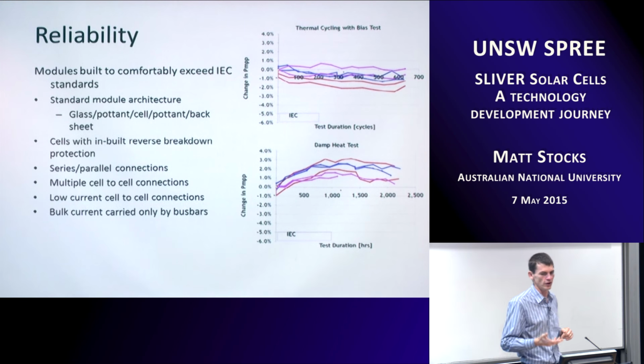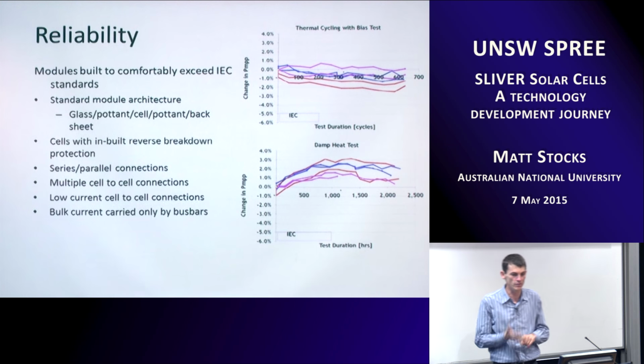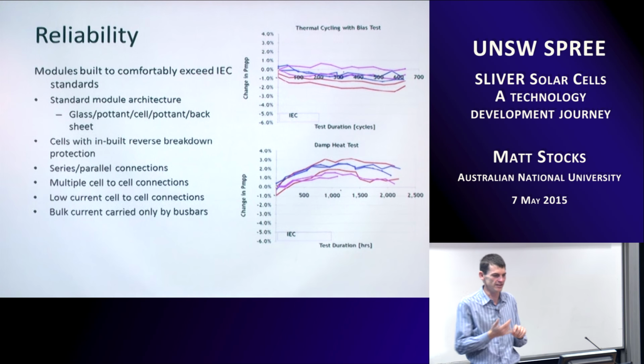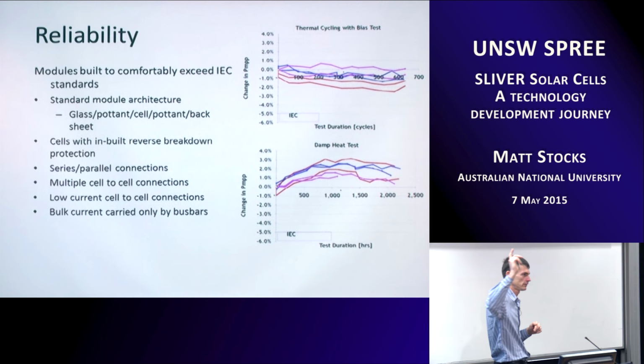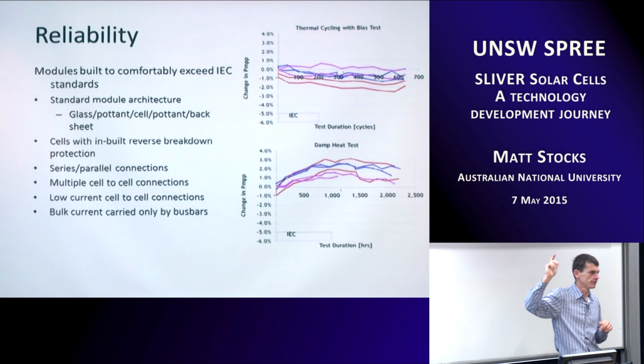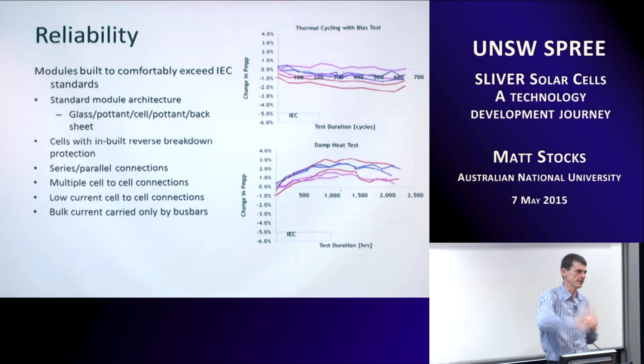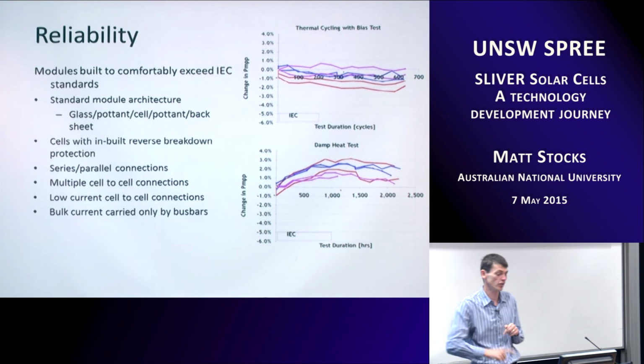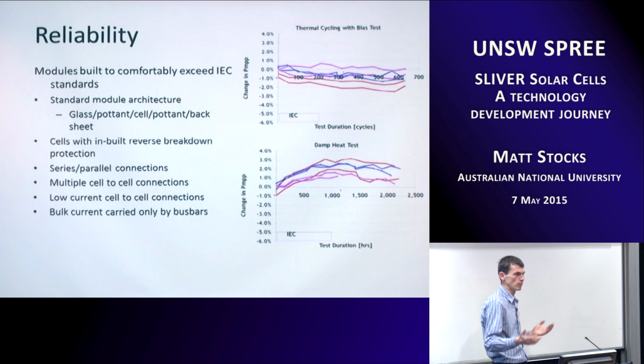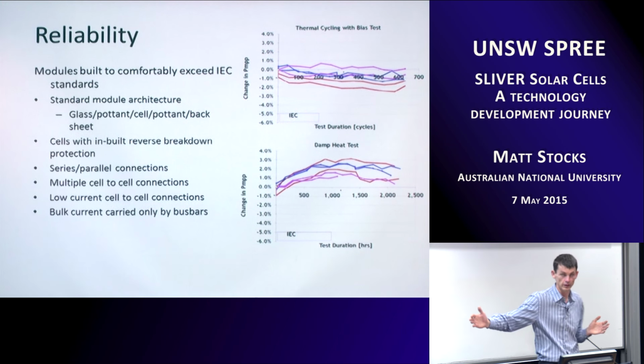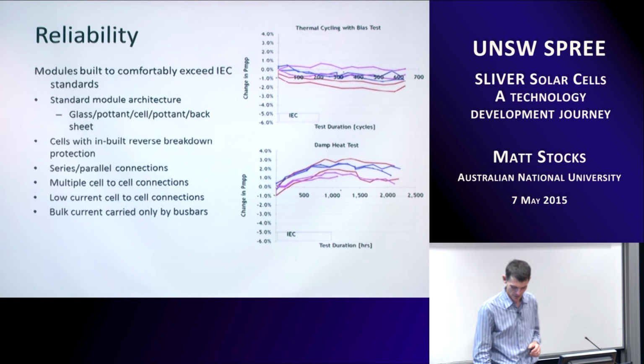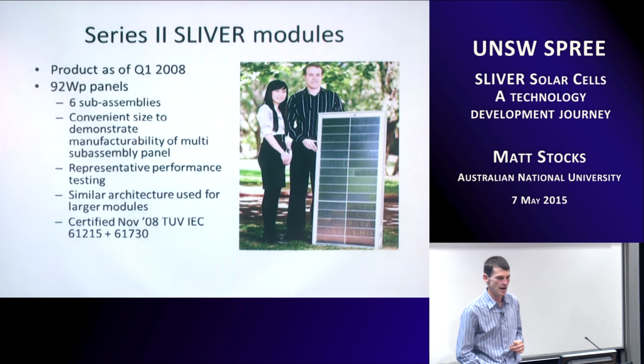So with this new cell design, this new module design, we could push our reliability testing. So IEC standard testing involves thermal cycling from plus 85 degrees at 85% humidity back down to minus 40 degrees, and then up and down and up and down on a 6-hour cycle. So it takes quite a long time to get through a large number of cycles. You're probably talking 6 to 9 months of testing on here, but we could see that the modules could last very long periods in those, could handle the damp heat, so extended periods at 85 degrees, 85% humidity. We could demonstrate those sorts of things. So again, the sorts of things that get marketing happy.